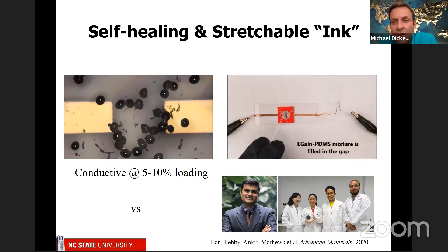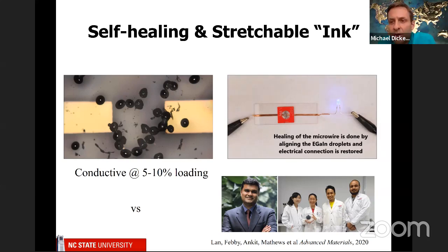Remember, it's not conductive. Just because you have liquid metal in there does not make it conductive. However, if you apply the voltage, you can assemble those particles and heal it, making it a metallic conductor, and then you can cure the silicone, which will heal it mechanically. And so this is cool because if you have a damaged circuit, you could just put some of this ink in, heal it, and it will be stretchable and highly conductive.